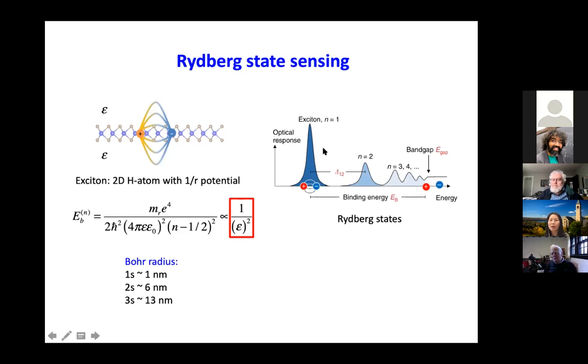those absorption spectra. So what I would like you to pay attention to is how they respond to the background dielectric material. So if we embed this in some kind of a dielectric background, we expect those binding energies to scale with the dielectric function of the background, right? And in the simple case, it just goes as 1 over dielectric constant squared, so exact detail may vary depending on how we treat this, but the take-home message is that the binding energy and also the spectral weight are very sensitive to whatever you put around this material. So therefore, the spectrum of those excitons, electron-hole pairs, is a very good probe of what's going on nearby.